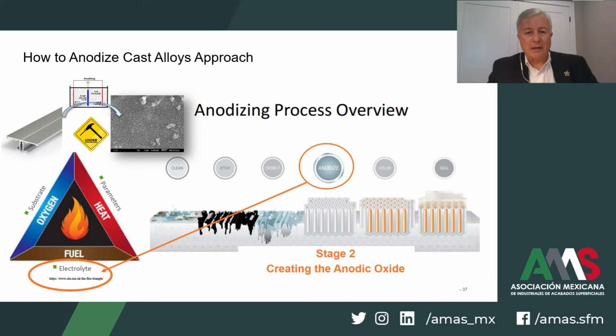The second stage is to optimize the sulfuric acid anodizing electrolyte, and this is done with some new additives that are incorporated into the solution that provide a range of benefits, but primarily focused toward creating and developing a pore structure that is similar to what we can easily create on the wrought alloys, while also limiting the attack of the sulfuric acid electrolyte on the casting alloy, which is detrimental to the formation of the proper anodic layer.